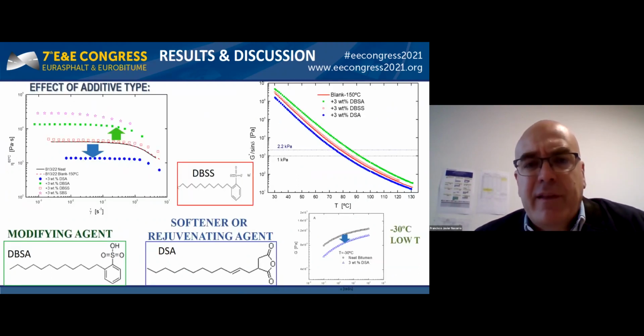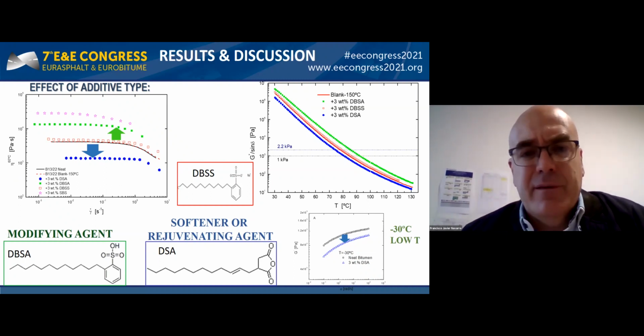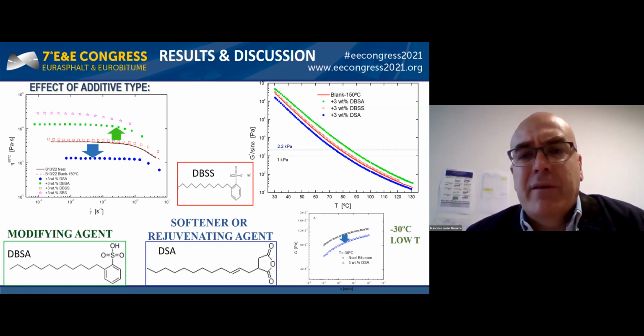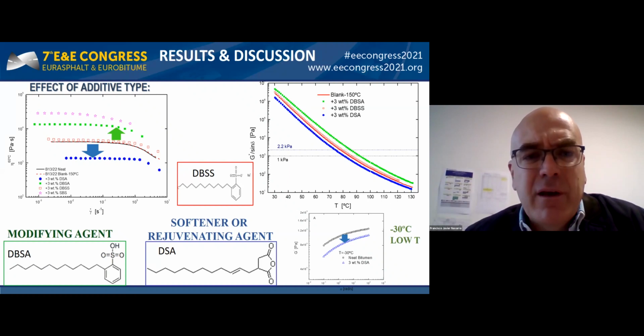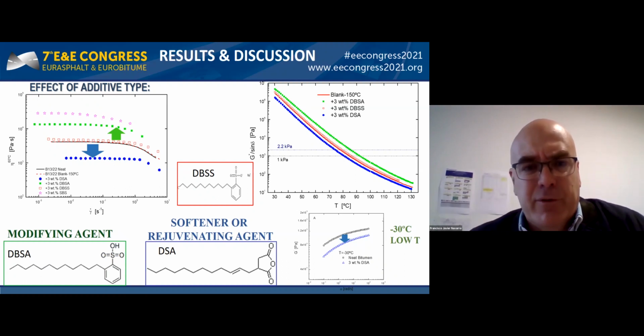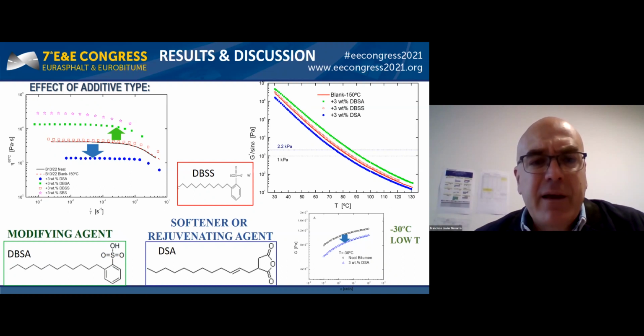The effect of both additives at high in-service temperature may be analyzed by means of flow curves at 60 degrees. When analyzing the unmodified binder, it is clear that the blank sample only undergoes a slight increase in viscosity due to bitumen oxidation during processing. However, DBSA modified bitumen presents a remarkable increase in the Newtonian viscosity, reaching values very close to those of SBS modified binder. On the contrary, DSA modified bitumen undergoes a completely different effect and clearly presents a notable drop in viscosity values.